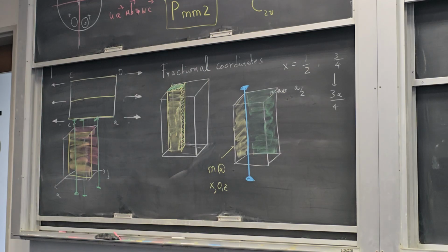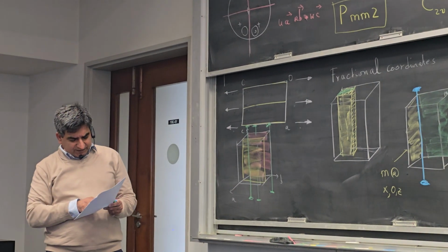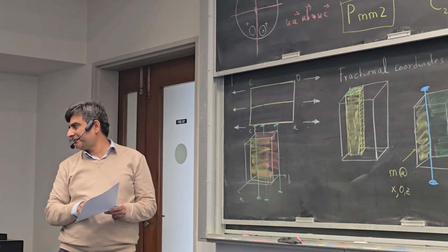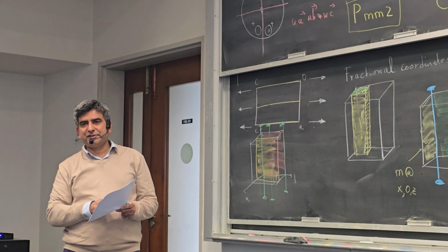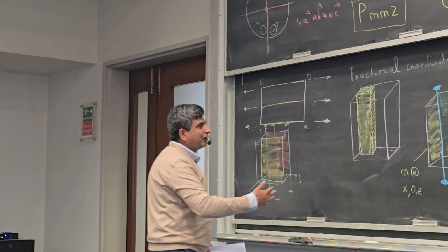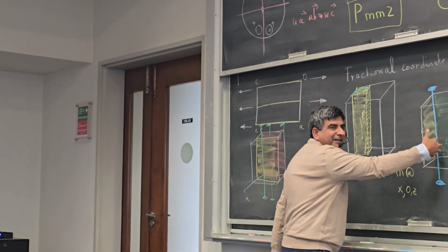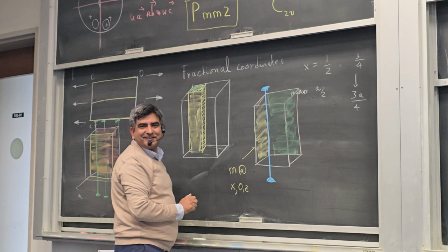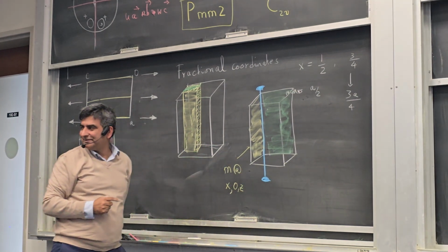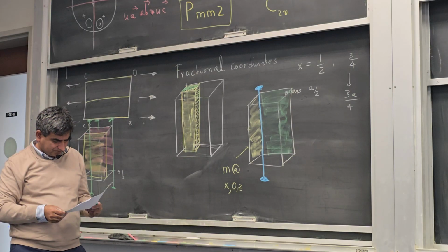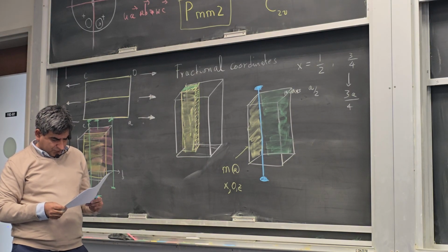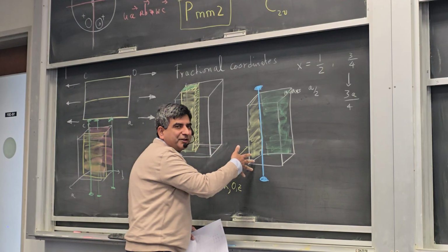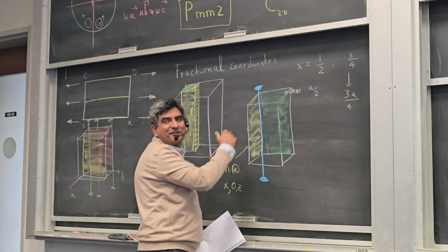So now what's going to happen is that these are the basic symmetry operations. Now on top of that, you have additional generators, which will generate all the symmetry operations inside this space group. Those generators are: one is do nothing, so you do nothing on these symmetry elements. The second is you do a translation 1 0 0, a translation of all of this by 1 unit along the a-axis. That will make the front face a mirror plane, and this will make this axis also a 2-fold axis of rotation. You can also have a translation of 1 unit along the y-axis, and a translation of 1 unit along the z-axis.